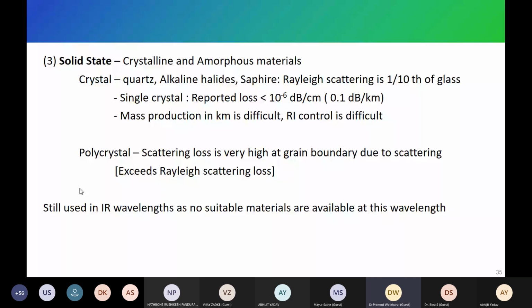Actually, we have crystalline and amorphous materials, right? Crystalline is where molecules are nicely arranged. That is crystal. Where they are loosely arranged, that forms the amorphous material. So crystals actually are very, very good for losses. Ultra low loss, 0.1 decibel per kilometer, very low. Just for your reference, we generally look for 0.2 decibel, right? 0.18, 0.19 decibel per kilometer. We say, okay, very good fiber. But if you use crystal for optical communication, you get only 0.1. So nearly a 50% advantage there.